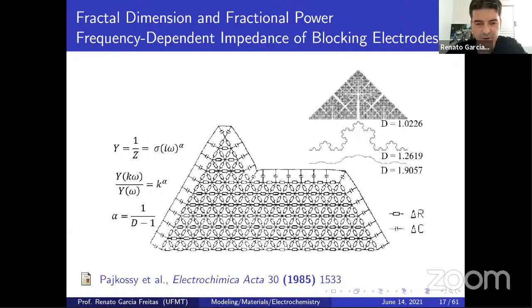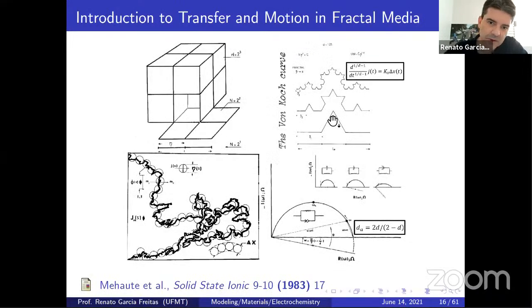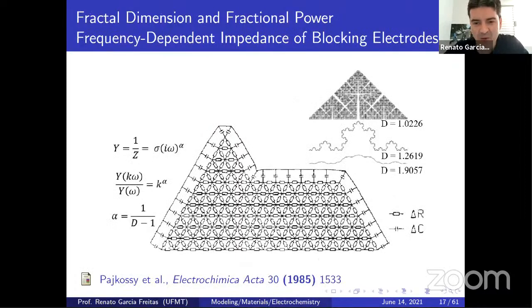Some authors consider it as beta, but it's the alpha of the CPE, responsible for the depression of the semicircle. And the alpha is 1 divided by the fractal dimension minus 1. So for a surface like this one, a Koch surface, remember the von Koch, which in the paper is called the monster of the von Koch surface. For the monster of the von Koch surface, we have several fractal dimensions: a very smooth one, like 1.02, a rougher one, 1.26, and a very rough one, 1.9.